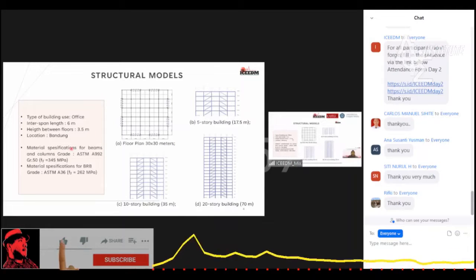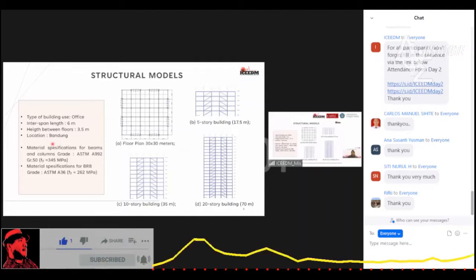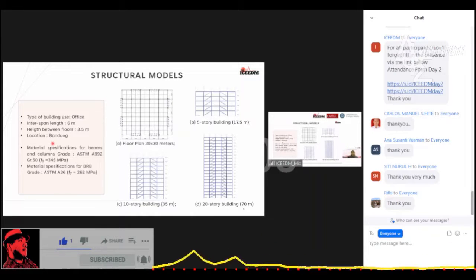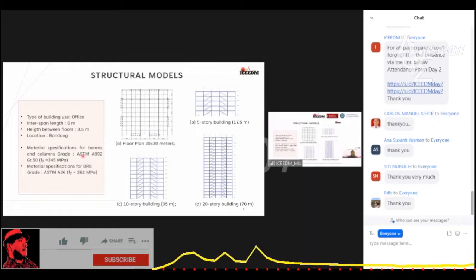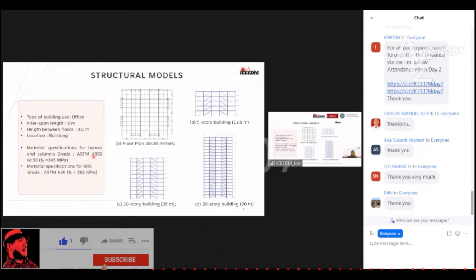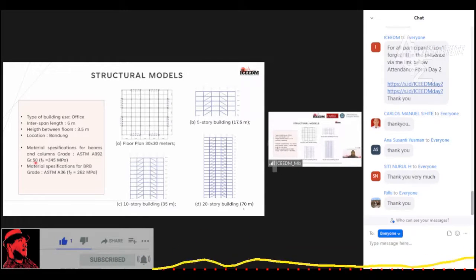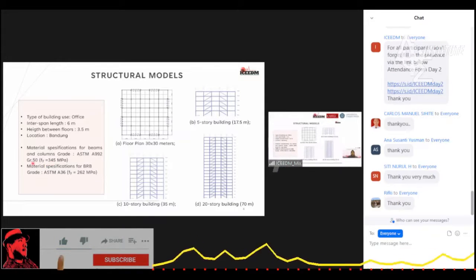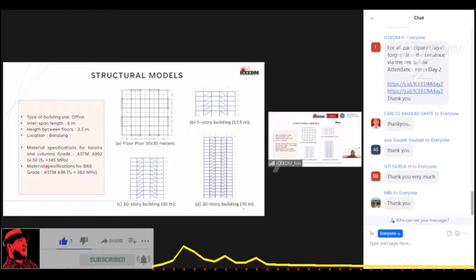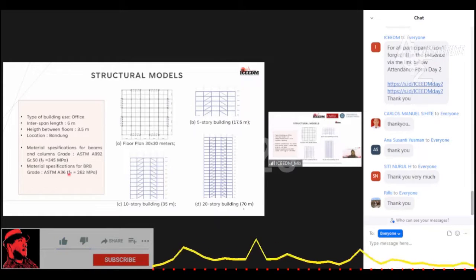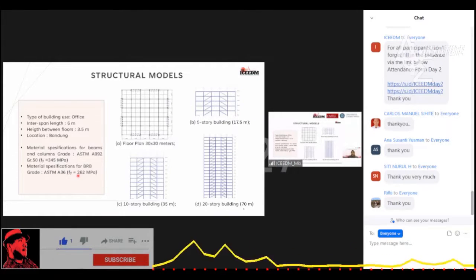And this is the material specification. The material specification for beams and columns uses ASTM A992 grade 50 with a yield stress of 345 megapascal. And the material specification for the BRB steel core uses ASTM A36 with a yield stress of 262 megapascal.